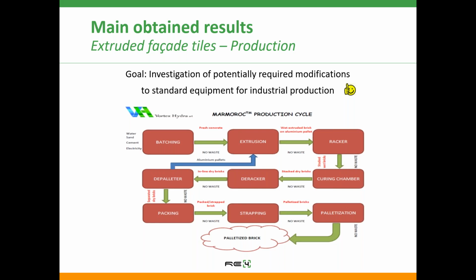Fresh concrete is put inside a hopper, and on the other side of the extruder, aluminum pallets feed the extruder, and then the fresh concrete, shaped in its final shape, is conveyed via a system of conveyor belts inside a curing chamber. It is basically a single atmosphere environment where the parameters of temperature and relative humidity are strictly controlled. Temperature can be increased by supplying it from the outside in a controlled manner if you want to speed up the cement hydration reaction.